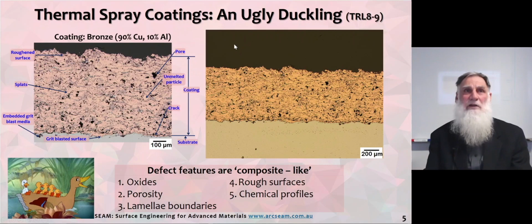So first of all, let's look at a typical microstructure of thermal spray coating. On the left-hand side, we have a coating. This is bronze of 90 copper, 10 aluminium. You see the roughened substrate. Sometimes you may see grit entrainment. You see the lamellar type structure with cracks, unmelted particles, pores, and we define these microstructural units as splats.